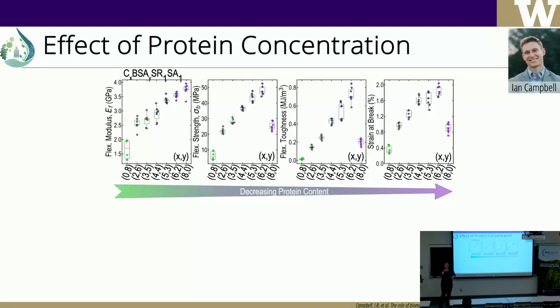Thanks very much. So seeing as you're relying on extensive hydrogen bond networks, where hydrogen bonds are very dynamic, in particular in these systems, I'm interested in aging effects. Yes. These are very, very good. So in that program that I presented to you, the collaborative, we do have aging in terms of cycling, heat pressure cycles, humidity cycles, UV also, because we may have also some degradation of these materials with light as well. So it is part of the 4-year project to also assess the cyclic behavior or stability, I guess, in different conditions. Definitely the losses and form and reform events of hydrogen bonds, I think, are very delicate to attempt to quantify. But we're going to give it a try and see.